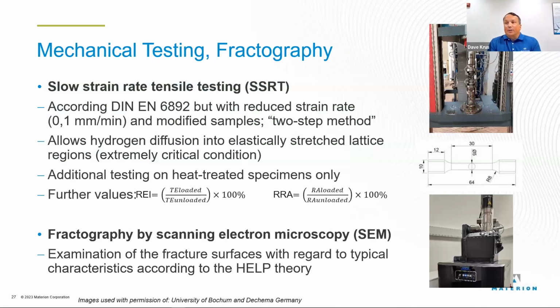And then the next thing we looked at was slow strain rate testing. As I mentioned, the slow strain rate, it's not a normal tensile test. You can see the tensile bar there just to the right in between the two photos. It's not pulling that at speed like you do in a production facility. It's a slow tensile test, which allows some defects to form and the hydrogen to move into those defects.